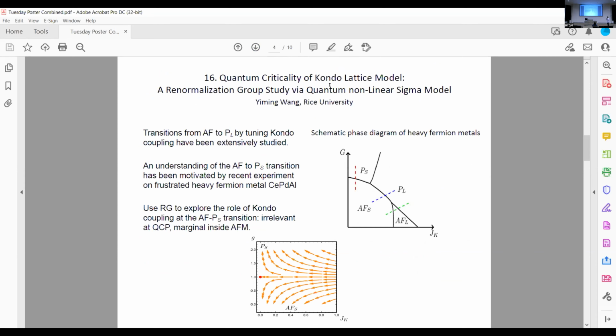Hi everyone, I'm Yiming Wang from Rice, and my work is about the quantum criticality of Kondo lattice models. This work is motivated by a recent experiment on the frustrated heavy fermion metal, cerium palladium aluminum, and we began to investigate the transition from the antiferromagnetic state to the paramagnetic state with small Fermi surface, which is a frustration-driven transition. The method we use is the renormalization group technique to investigate the sigma model in the presence of the Kondo coupling. And the result we find is that the Kondo coupling is marginal inside the AFM phase, and it is irrelevant at the quantum critical point between the AFM and the PS state. For further details, welcome to see my poster. Thank you.